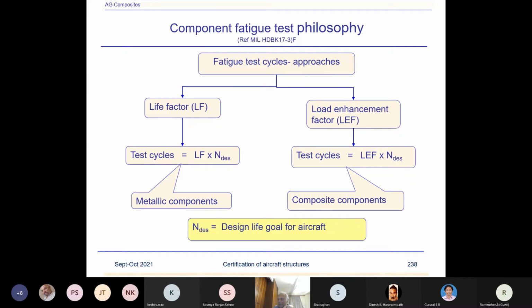So suppose a factor of 10 and you have 50,000 flights multiplied by 10, so 500,000 flights. But what happens when the loading is done? In one flight, there could be 10 cycles or more cycles. So that means your number of cycles grow significantly. And the danger is that due to that large number of cycles when you are applying, the failure may occur in the fittings or somewhere else. So generally, purely the life factor is not applied to the composite. And next slide, I'll show you.